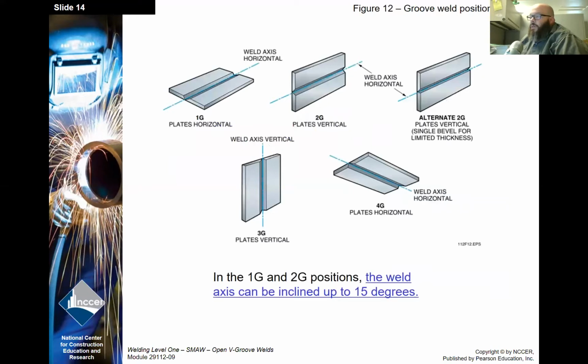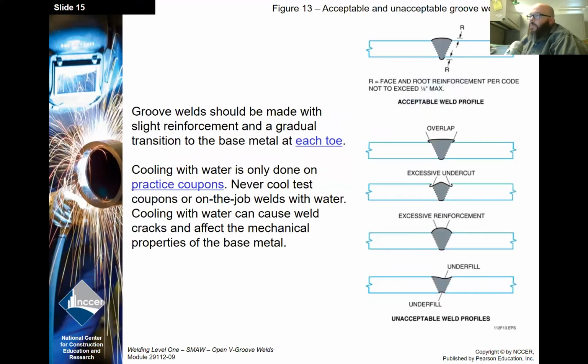In the 1 and 2G positions, the weld axis can be inclined up to 15 degrees, again just like with the V-groove with backer. Groove welds should be made with slight reinforcement and a gradual transition to the base metal at each toe. Cooling with water is only done on practice coupons. Never cool test coupons or on-the-job welds with water. Cooling with water can cause weld cracks and affect the mechanical properties of the base metal. This goes for both the backered and the open V-groove. Never cool them in water.